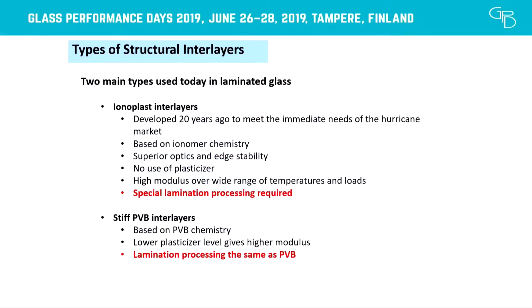They have superior optics and edge stability, and there's no plasticizer. It's because there's no plasticizer that you have such great edge stability. And the modulus maintains its high modulus over a broad range of temperature and load durations, which is why it's used in a lot of extreme applications. But because of its unique chemistry, some special processing is required, and I'll go into that in a little bit more. Stiff PVB interlayers are based on PVB chemistry. They just have a lower plasticizer content, and they have very high modulus. The lamination process is the same as PVB, so that's the advantage of it. There's no need to change your lamination process.